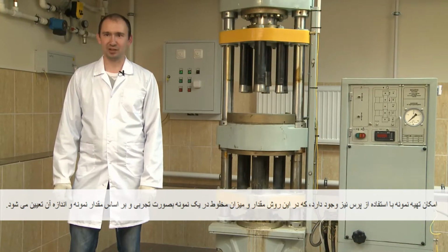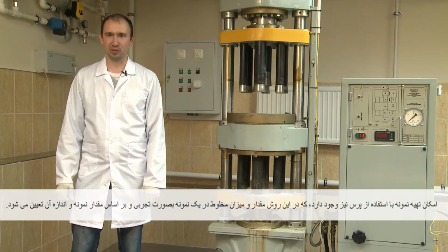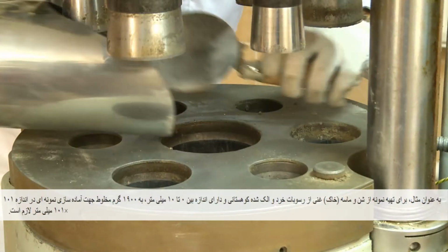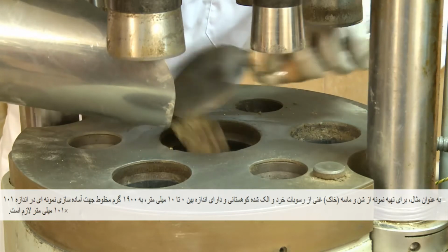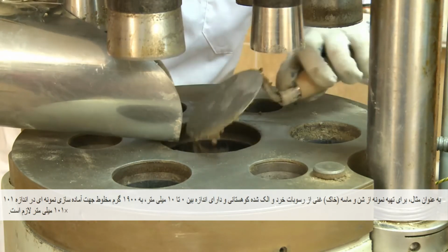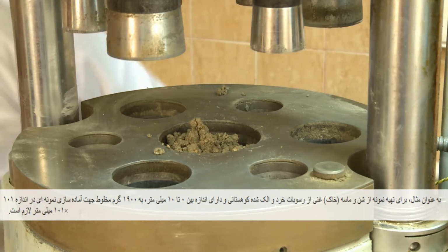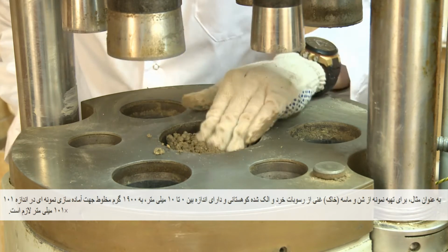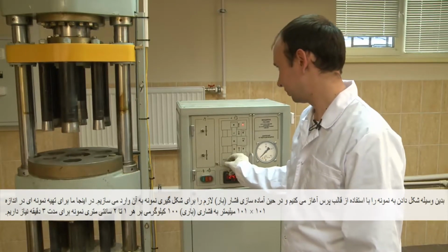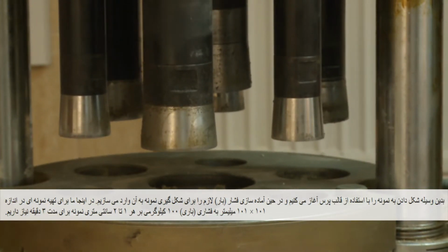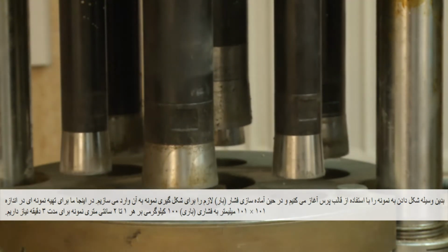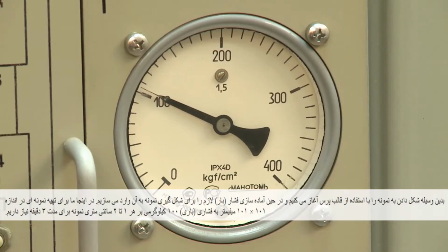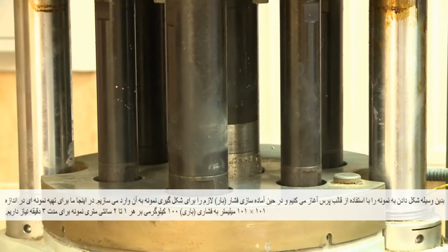It's allowed to produce samples using the press when the amount of the mixture per one sample is determined empirically based on required sample dimensions. For example, we need 1,900 grams of mixture to produce a sample with dimensions 101 by 101 millimeters to produce samples of improved sand with screened breakage of sedimentary rocks of fraction 0 to 10 millimeters. Now we start forming a sample in a die mold and specify loading parameters acting when the sample is formed. In this case, necessary loading for a sample with dimensions 101 by 101 millimeters is 100 kilograms per 1 centimeter squared over the course of 3 minutes.